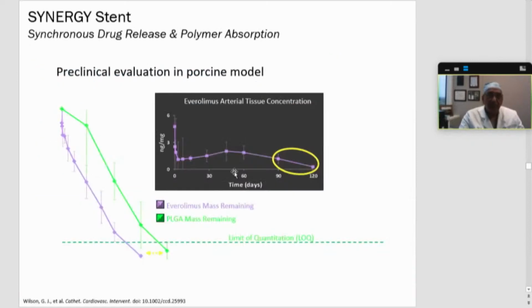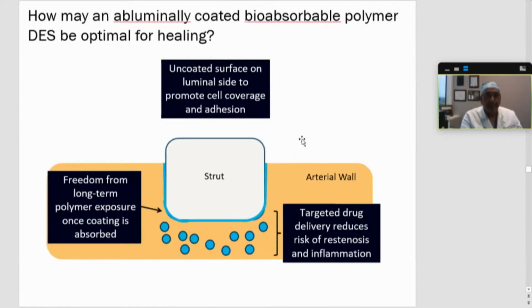So as I just explained, the drug elution actually finishes at about 3 months with the Synergy stent design, and the polymer is completely absorbed at about 4 months. So that polymer is also gone. Obviously, the drug has already eluted, and you can clearly see that the tissue levels of everolimus are nicely maintained up to 3 and possibly 4 months. So this is the fundamental idea. You have this uncoated surface on the luminal side to promote cell coverage and adhesion. There is freedom from long-term polymer exposure once the coating is absorbed. And then obviously targeted drug delivery reduces the risk of restenosis and inflammation on the outside.